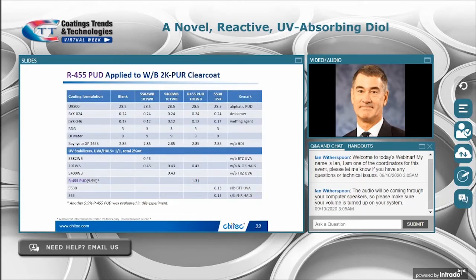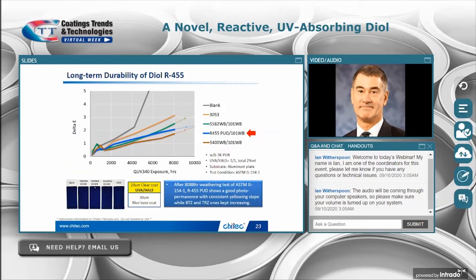Okay, in this experiment, we're looking at R455 in a waterborne 2K clear coat system. And we're testing it for color retention. It's over a dark blue base coat. And the diol R455 is pre-reacted into the waterborne PUD. So we are comparing this diol UVA PUD to 3 systems with different freely added non-reactable UVAs.